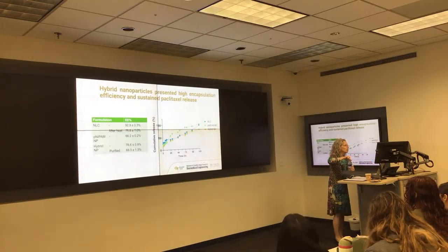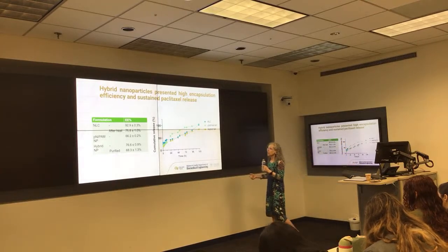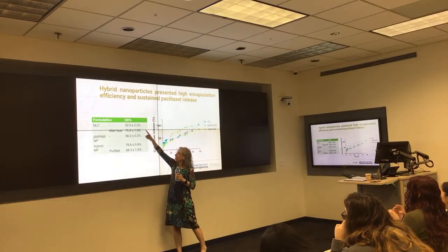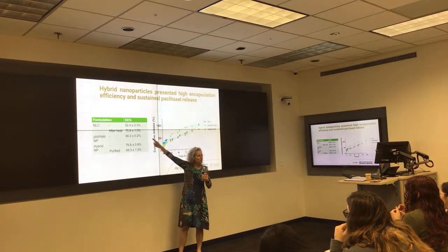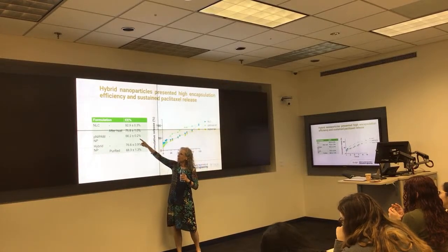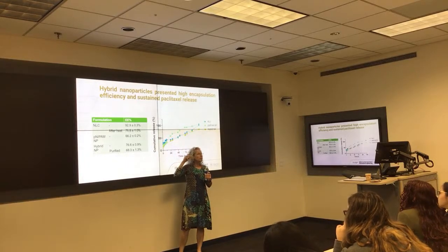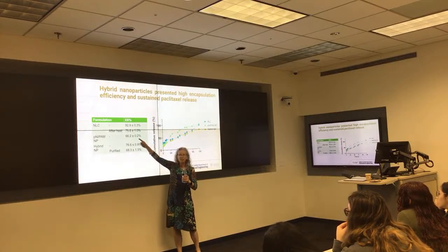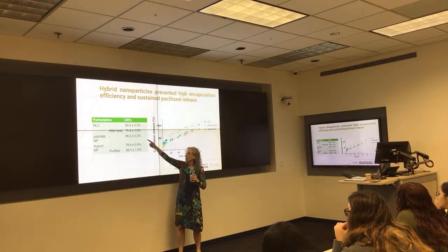Okay, so she also wanted to look at loading efficiency. So for her solid lipid nanoparticle, she had really nice loading efficiency, right around 93%. But when she heated them up for polymerization, that dropped to 75%, so she lost some of the drug. If she took the polyNIPAM nanoparticle, so she formed just the particle that I talked about at the very beginning, the low polymer density polyNIPAM nanoparticle, she actually saw 66% loading efficiency, which is a little surprising, but very good.